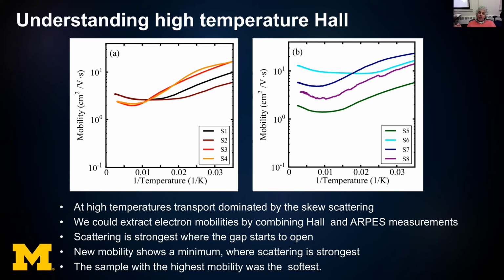And maybe this is not surprising because the skew scattering is really dominant, and the mobilities are lowest when the gap is about to open up, and when you estimate mean free paths, they are getting close to the lattice constant of the material. There was one pathological sample which showed high mobility, or not high, but relatively high, and this one turned out to be the softest of the samples we had, and we don't particularly trust that sample because it might be highly disordered.